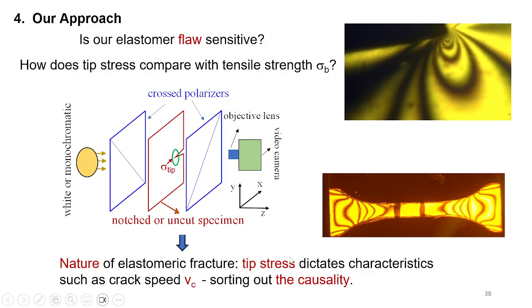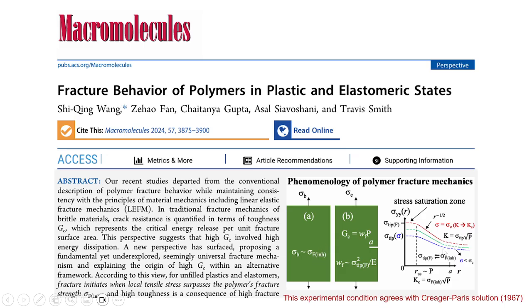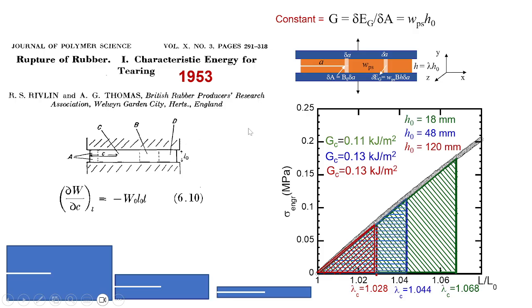So some of the details are already published in this paper. Basically, one of my beginning efforts was to clarify the meaning of the Rivlin-Thomas experiment. What they find is they do a pure shear. They find that independent of h naught, the crack will start to propagate at the same G. Okay, which has the implication that this is all a beautiful energy argument.